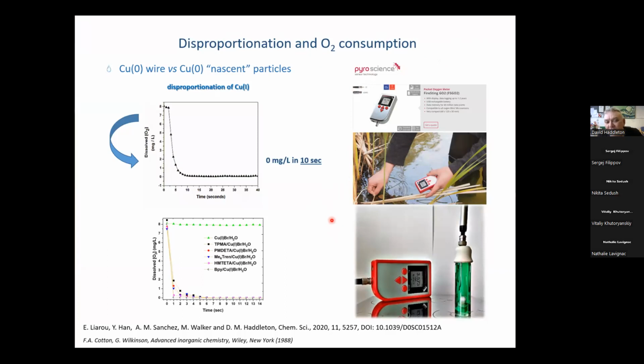And I said, well, we need to be able to measure it. And we found this little thing here, which is sold by a German company, Pyroscience. It's essentially sold for you to go around lakes and rivers and put it in to see the oxygen content, to see whether or not fish or biology can occur, or whether the oxygen levels have got so low that the fish can't survive. So essentially, you just poke it in and it gives you a reading. You can wave it around in air and it will just give you the oxygen level of the room.